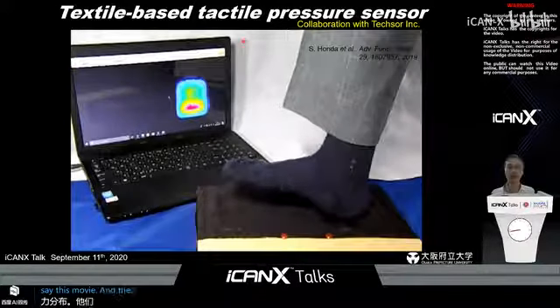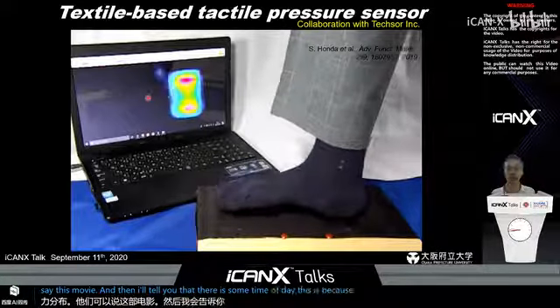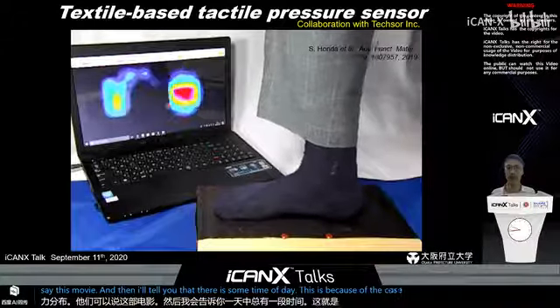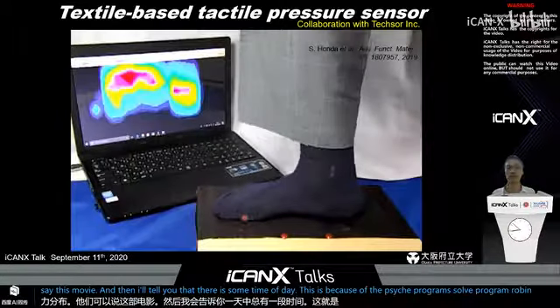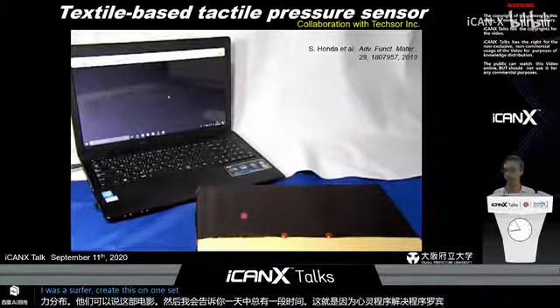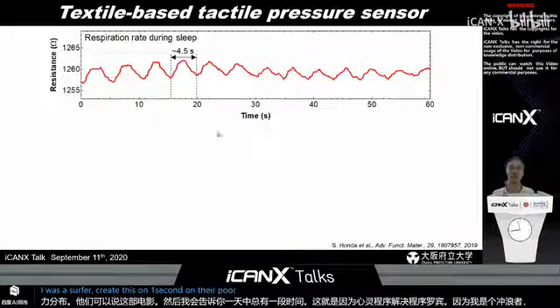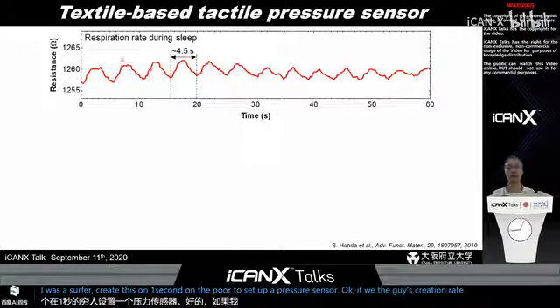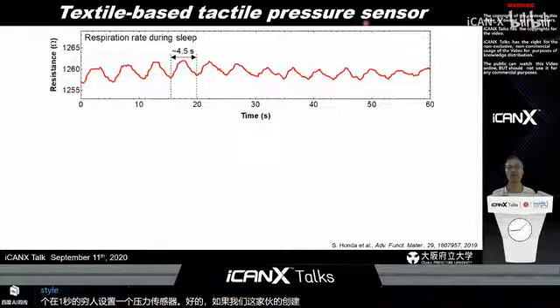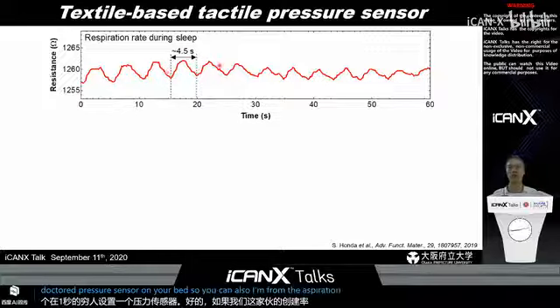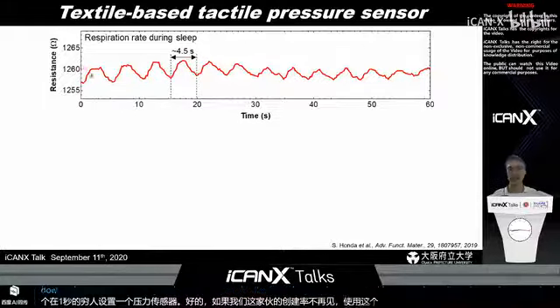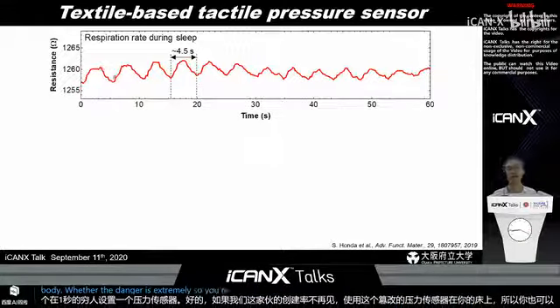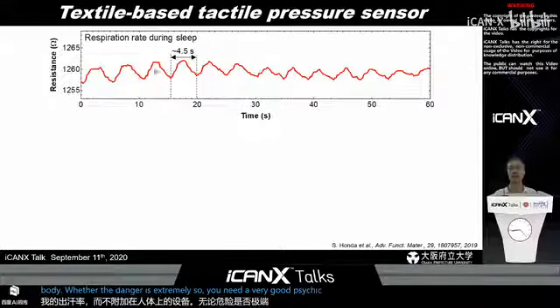And actually there is some time delay. This is because of the circuit problem, a program problem. The sensor response itself is very quick, less than 1 second. For this tactile pressure sensor, if we want to measure the respiration rate, by using this sensor on your bed, we can also monitor the respiration rate without attaching the device onto the human body. However, the resistance change is extremely small, so you need a very good readout circuit if you want to do this respiration monitoring.